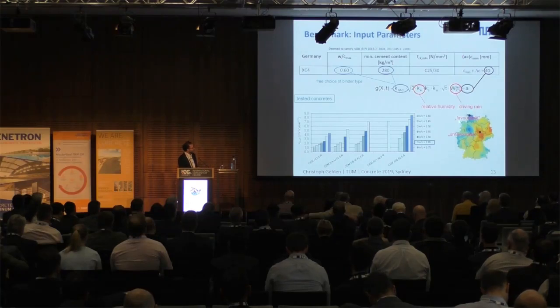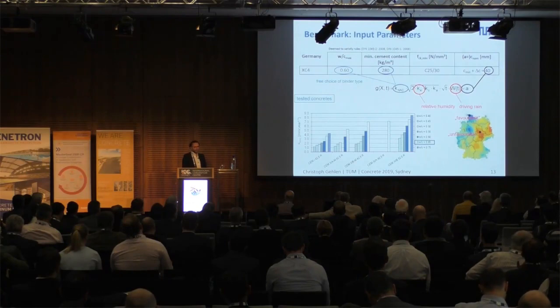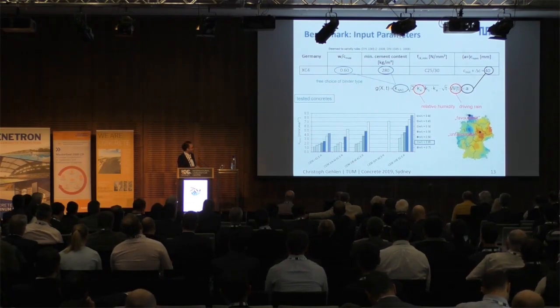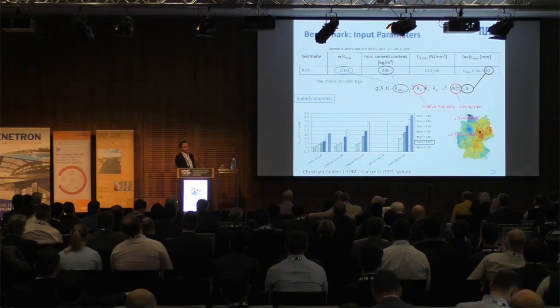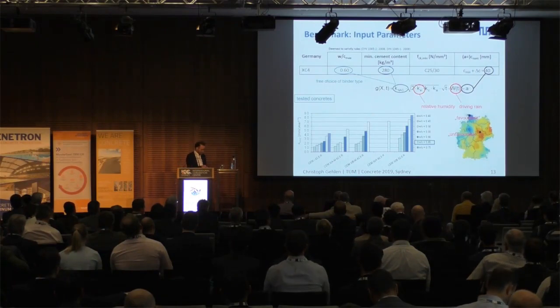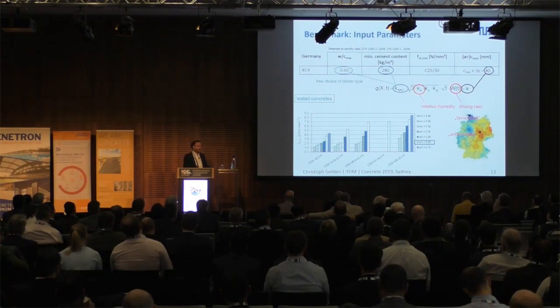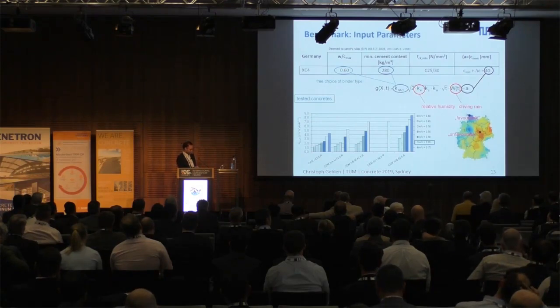And what we did is we calculated two situations, two design situations, one favorable and one unfavorable. Favorable means we took a very carbonation resistant concrete and put it in a very wet environment, because if it is wet, no carbonation, or at least slow carbonation, will occur. This is favorable. And for the unfavorable situation, we took a city or location in Germany which is very dry and linked this very dry spot to a very low carbonation resistance.